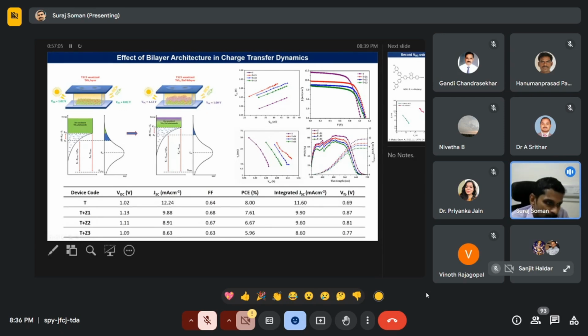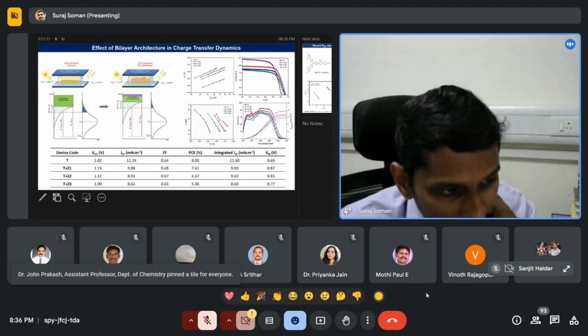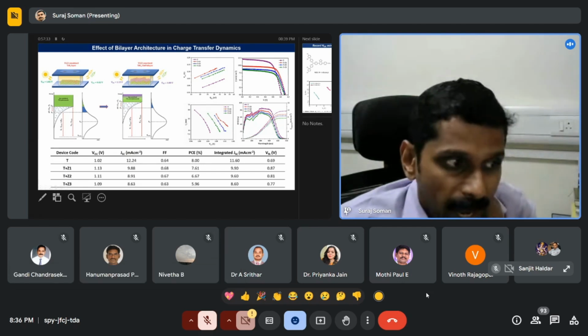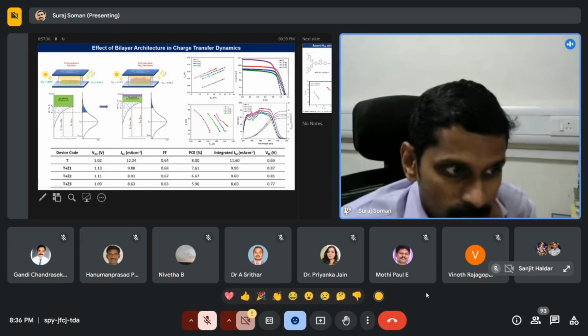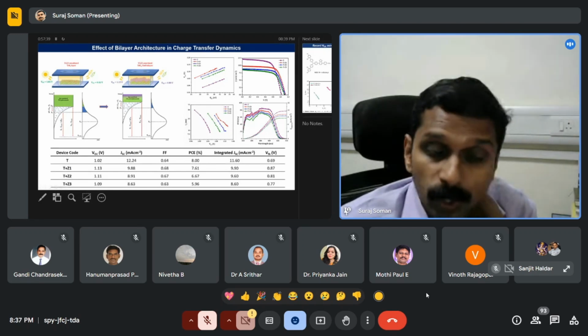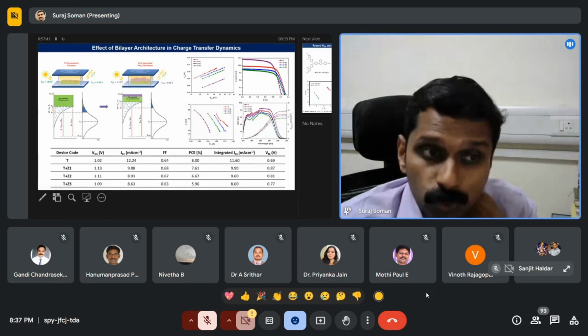And what we have seen is a very interesting behavior. Conventionally, in the energy diagram, this is for the normal control device where you are only having a titanium dioxide, you are having a Fermi level. The moment you put a zinc oxide on top of your titanium dioxide, there is a negative shift happening to the conduction band. And that is very clear from the capacitive measurement and also reflected in the voltage. You are getting a higher open circuit potential. The control device has a voltage of 1 volt, and the moment you put a bilayer like the zinc oxide, the voltage goes from 1 volt to close to around 1.13 volt, which is a huge increase.